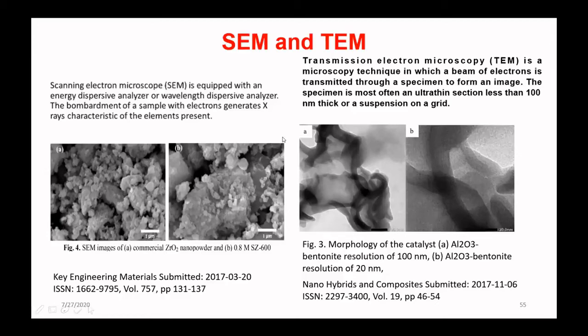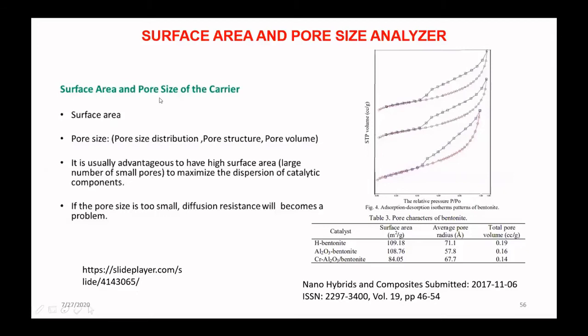Surface area and pore size of the carrier or matrix. Yes, pore size is very important, because if the pore size is too small, there is diffusion resistance in the process. It's usually advantageous to have high surface area to maximize the dispersion of catalytic components. So it's very important if we make a supported catalyst, for example, insertion or inclusion of metals into the pore or layer structure. We must know the pore of the materials that we will use for the process.